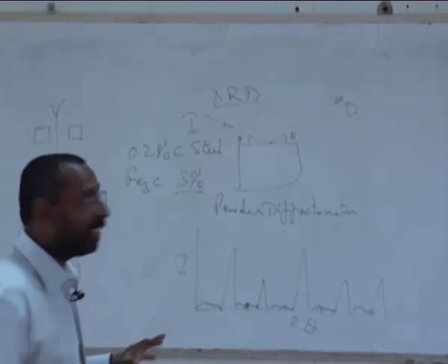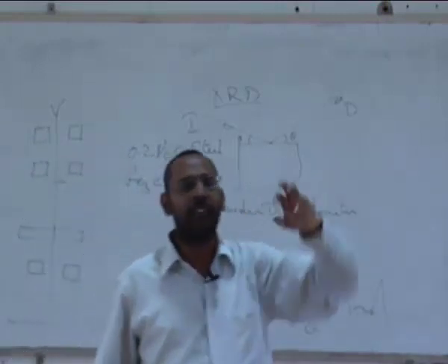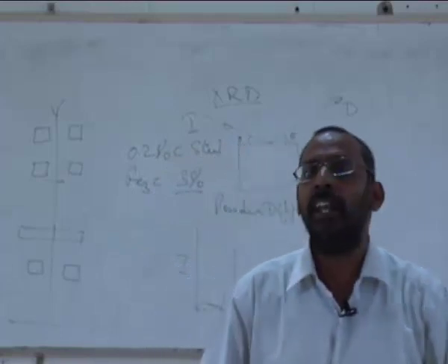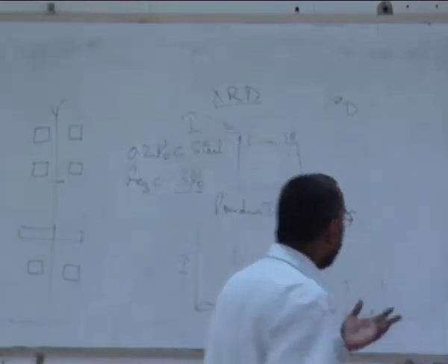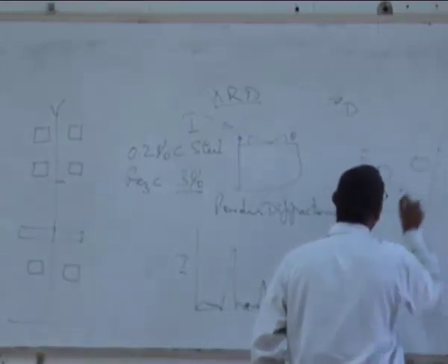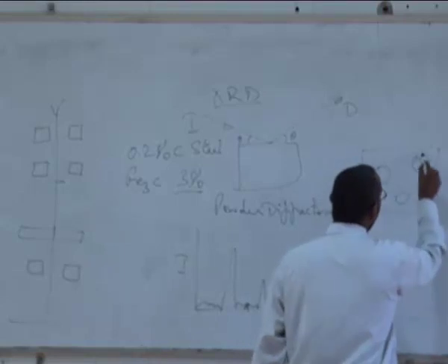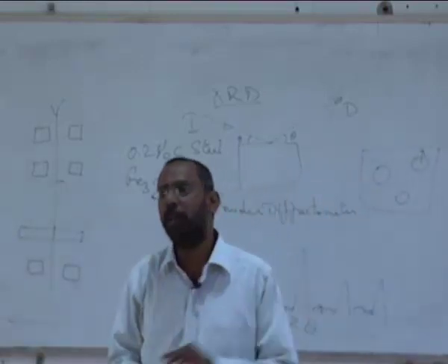So as a result, X-ray diffraction has that limitation that phases which have small volume fractions cannot be easily seen. And also the second factor that you cannot see is what I was just talking to you about. If you have a sample with some precipitates in it, and there is an orientation relationship between the precipitate and the matrix, this information you will not be able to see.